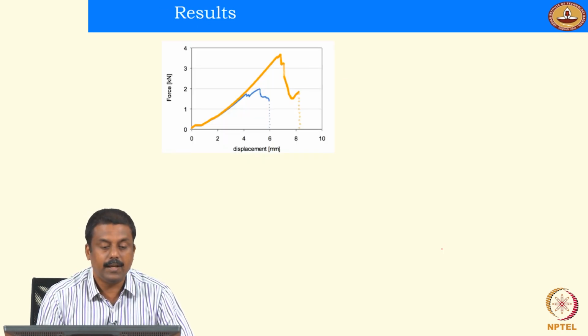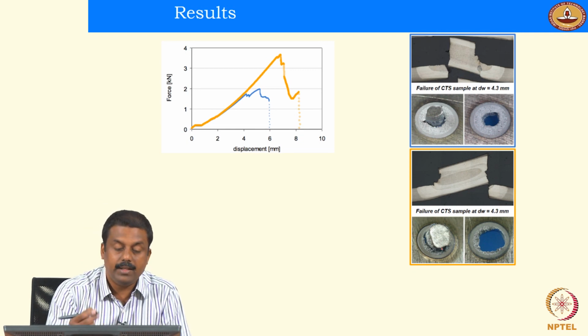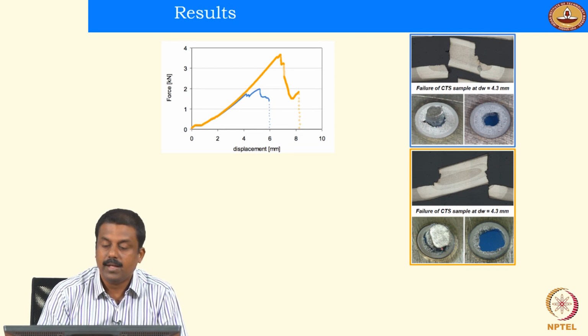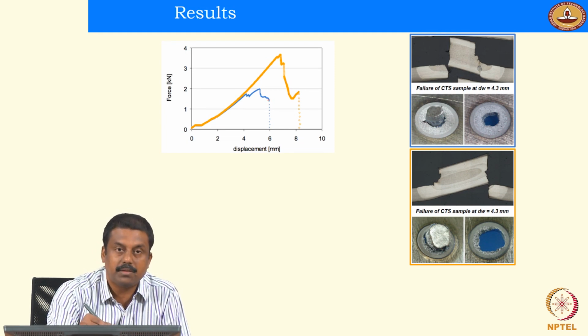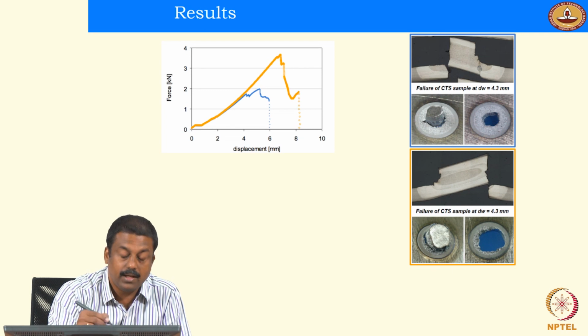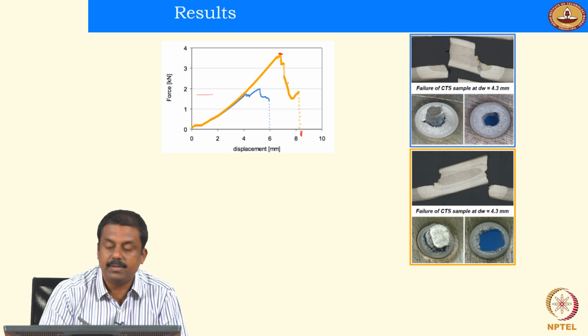You clearly see in the curves that the mechanical properties certainly improve. For example, the blue curve here shows the cross tension tensile test results, where the first pulsing shows very poor strength, whereas after applying a second pulsing your strength level increases significantly. You also have a high displacement. That means that the mechanical properties improve significantly.